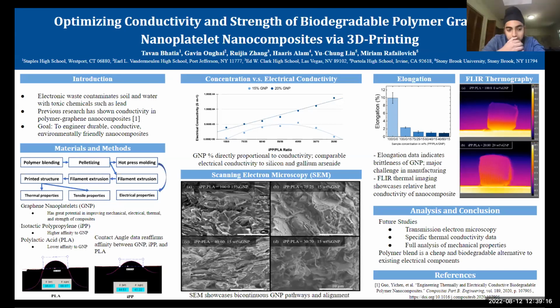So this contact angle imaging did reaffirm our data and our hypothesis. As you can see, the affinity for isotactic polypropylene was higher than that of polylactic acid. We also looked at SEM data, and you can see on our 75-25 and 40-60 samples that we have some circular domains, which we hypothesize are PLA, and we hypothesize that surrounded by those is isotactic polypropylene, which has the graphene aligned and embedded within it.